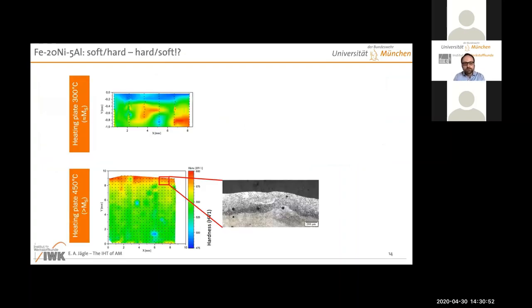And it turns out, if you look into this in even more detail, these are hardness maps for two different samples, one produced at roughly MS or maybe slightly below MS, and one definitely above MS. And you see that we have a flipping of the hardness gradient. This is a cross-section. At higher than MS, we have a high hardness in the last few layers and a lower hardness below. In this case, below the martensite start temperature, it's just the opposite. We have a lower hardness at the very top and a higher hardness at the bottom. There's clearly a difference in the microstructure if you look at this etched micrograph.